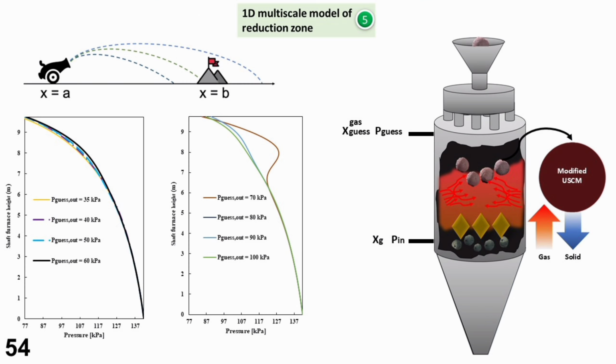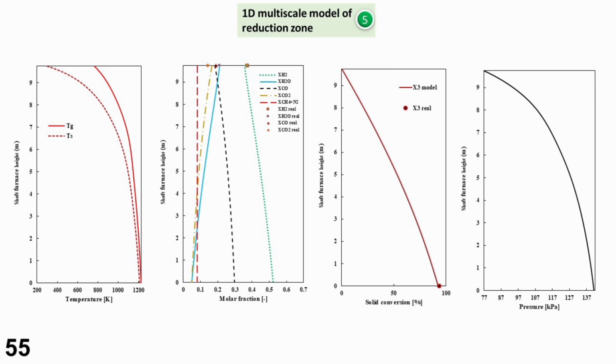Now, it's time to talk about the shaft furnace model, where we use the shooting technique. Previous models used constant pressure, and a few studies considered an equation for pressure variation. For the first time, we demonstrated the impact of pressure and observed how significantly pressure can affect our outputs. We validated our model with the Gilmore shaft furnace, which is located in the United States. This is the most commonly validated furnace because its data has been well proven to be reliable.